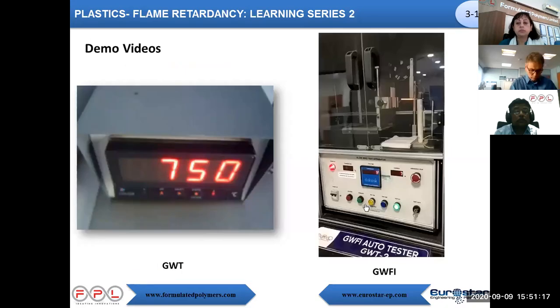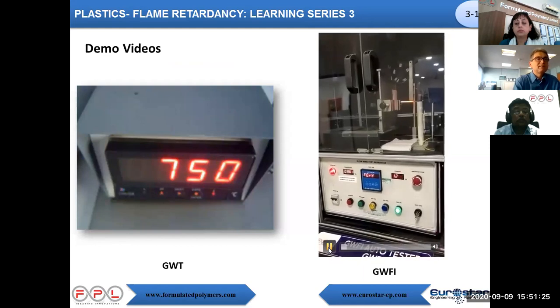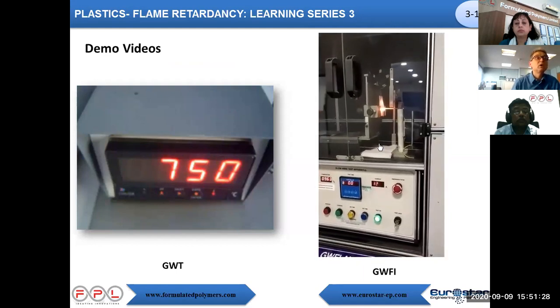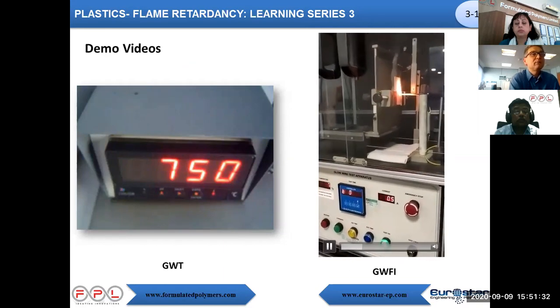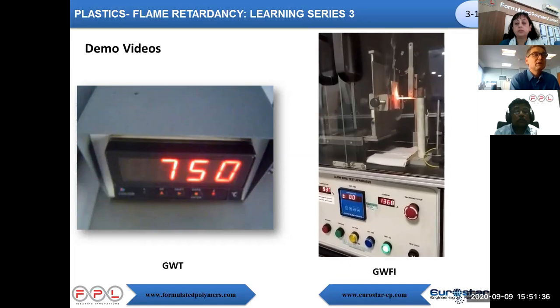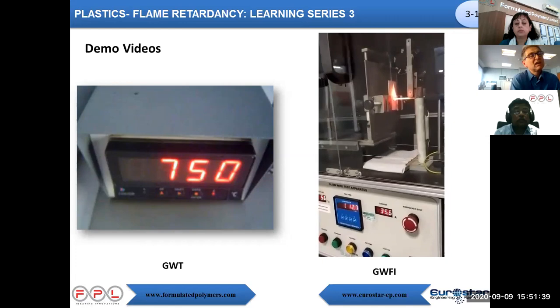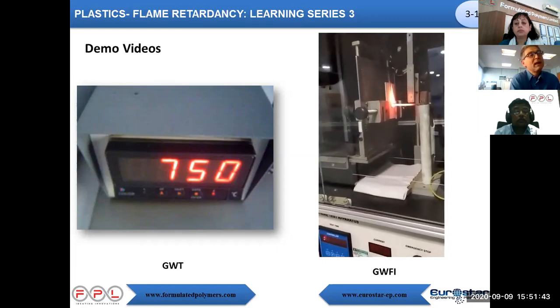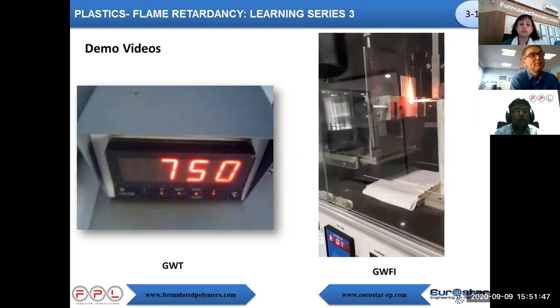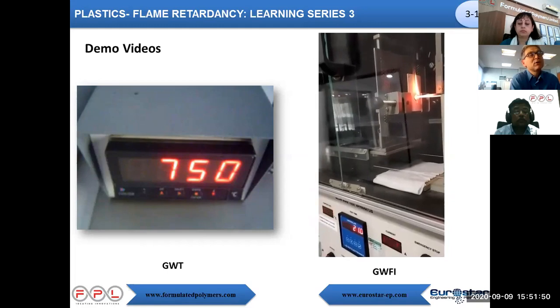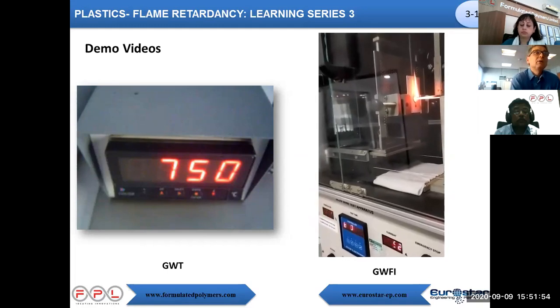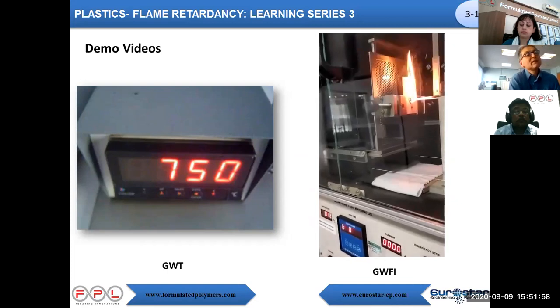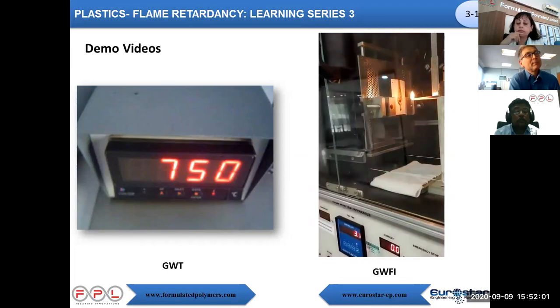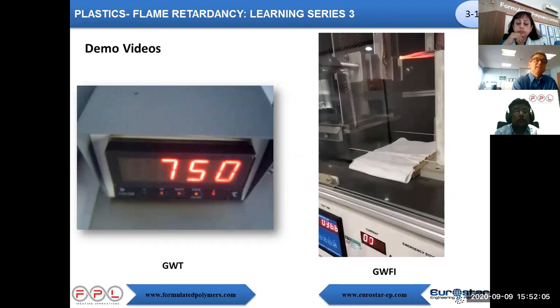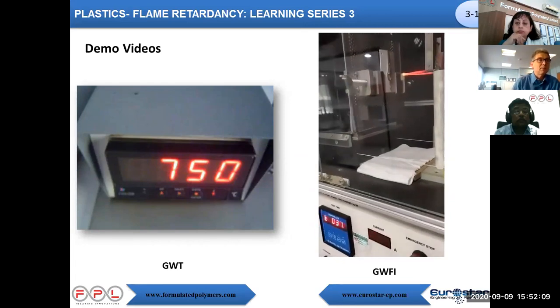Oh, sorry. Then you will see a test made in FPL India on their apparatus. So here the same, they are launching the test. The wire is applied to the plastic spot. You see immediately the wire is very hot. You see it's almost white, so it's 960 degrees C. And of course, at this temperature, polymer burns. You see the flame is formed. In this case, you see there is no flammable drips, which is a good sign. And after 30 seconds, the wire is automatically removed from the sample. You will see in this case that some material is carried in the nozzle of the flame, but almost immediately, the material is extinguished. So in this case, the test is really nicely passed.